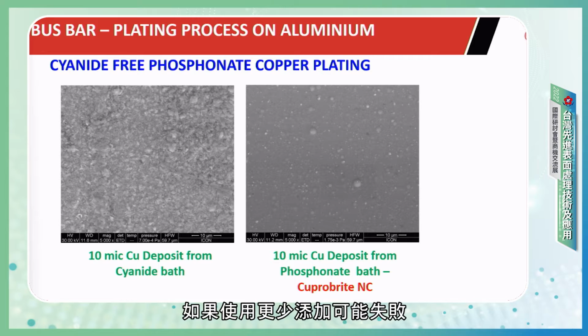If we use lower, there is a chance of adhesion failure. If we use more than excess, it will reduce the rate of deposition, and furthermore it changes the surface topography also.